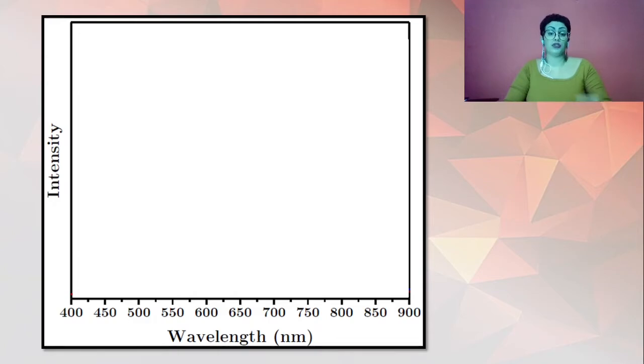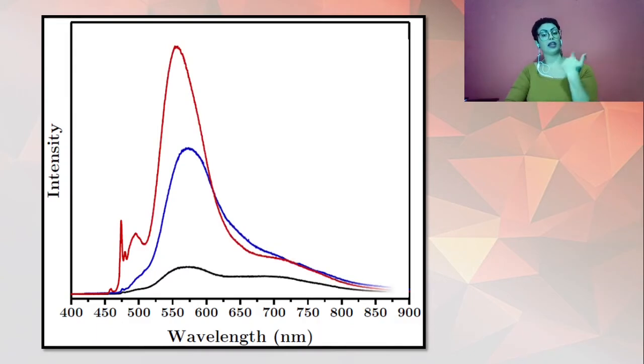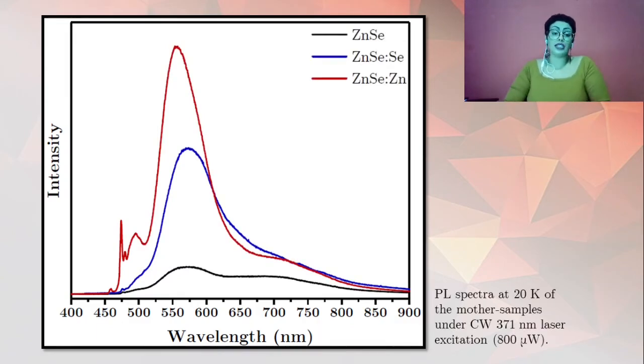The mother samples are non-luminescent, so they did not show noticeable luminescence to the naked eye under UV laser excitation at room temperature. Also, the PL spectra of the samples at room temperature did not show any bands, as expected. But as the temperature decreased, some PL bands became visible. In the low temperature PL spectra of the mother samples measured at 20 Kelvin, it's possible to identify excitonic peaks and two broad luminescence bands.